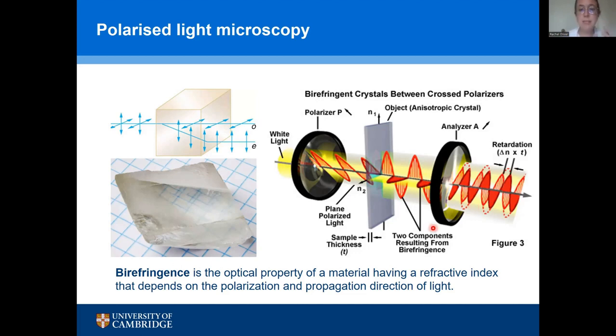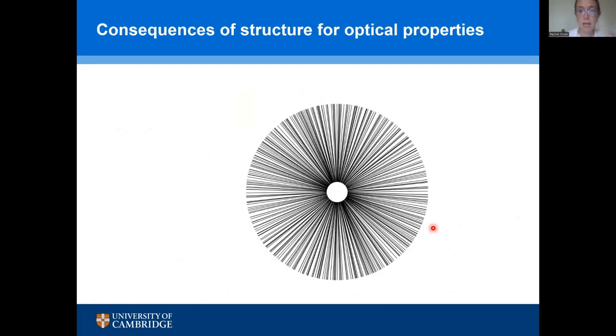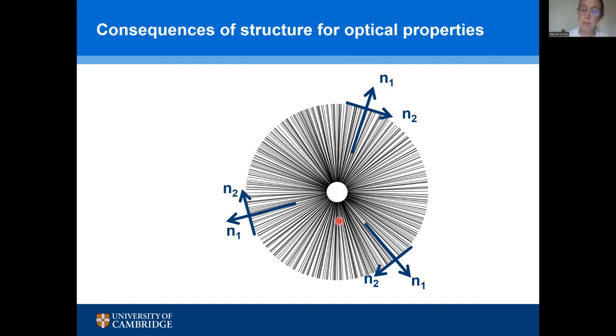Okay, so the fact that we can see features in polarized light microscopy means we now have a birefringent material. And that links back to the structure we were just seeing, with the radiating pores from that big central pit, because the refractive index will be different along the pores and across the pores. But because we have a radial structure, the anisotropy will depend on where we are around that circle, with the fast direction, i.e. the low refractive index, being differently oriented, being basically circumferential always as we go around the circle.